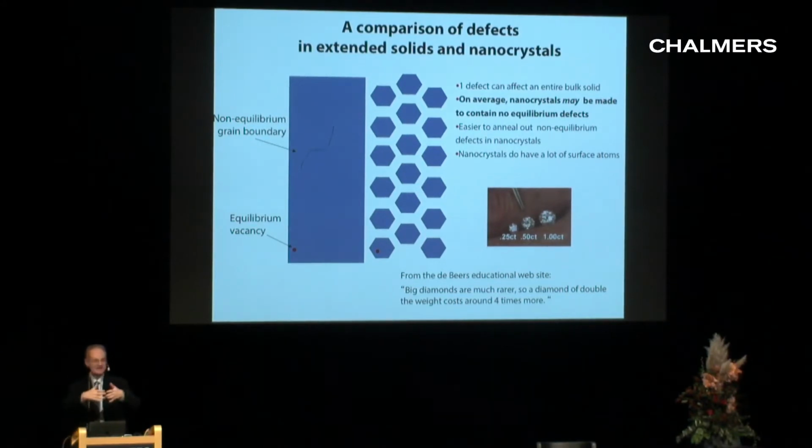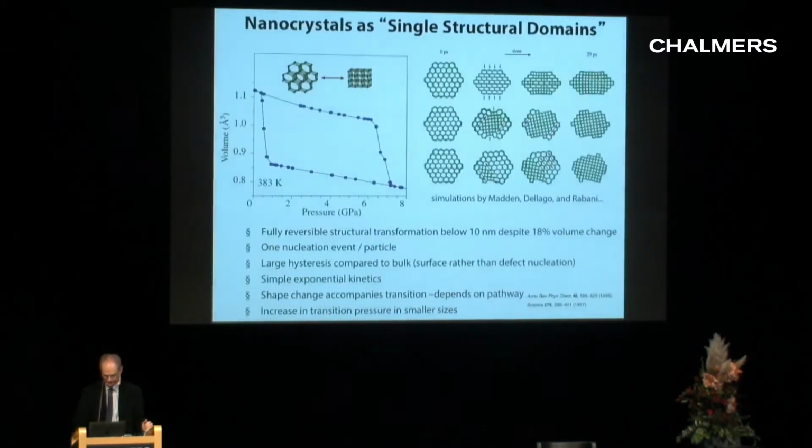So instead of wanting to have a really big crystal that's perfect, I can have a really tiny one. And for a tiny one, the time for a defect to anneal out should be very short. So if I combine the finite size and the temperature, it should be possible to make a really perfect tiny crystal. That doesn't mean you will always make a perfect tiny crystal. You have to actually do it right. But it is possible to make crystals where only one out of many millions will have any defect in them at all. So you can make highly, highly perfect tiny crystals.